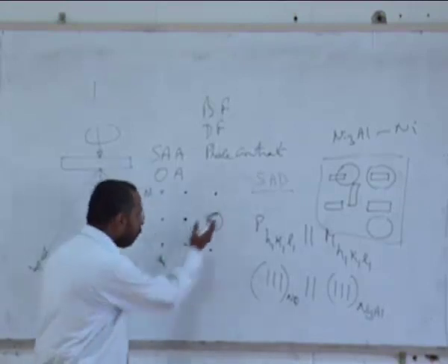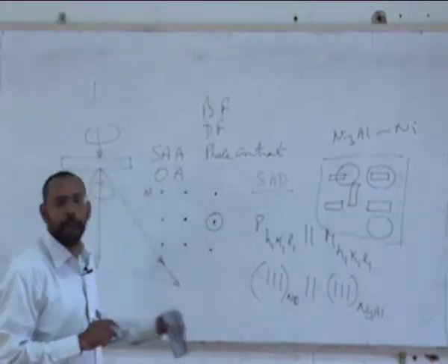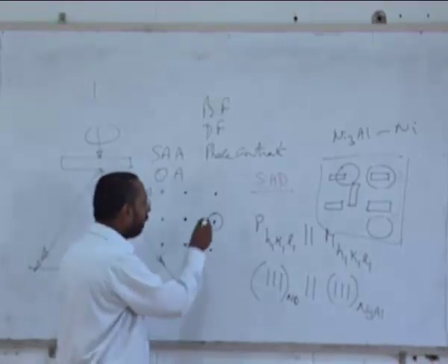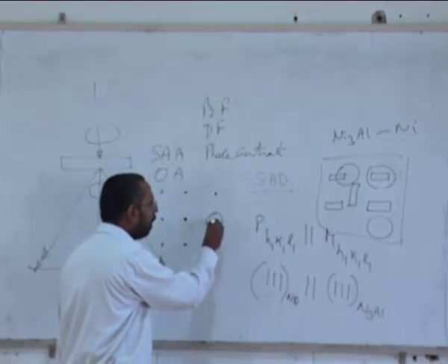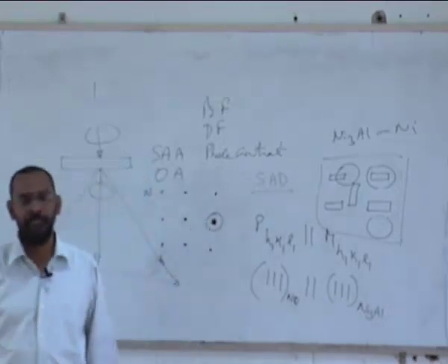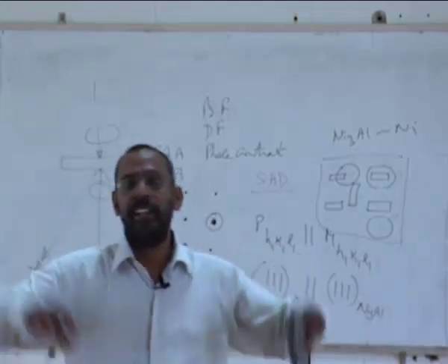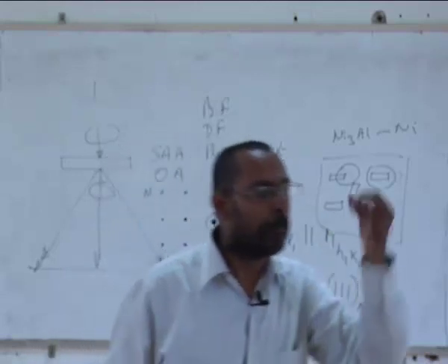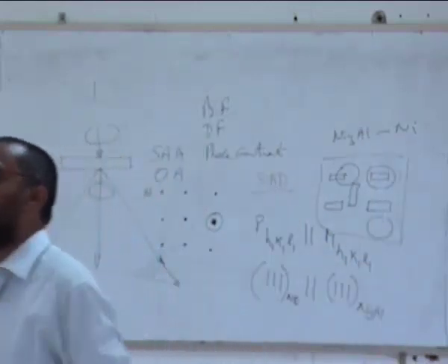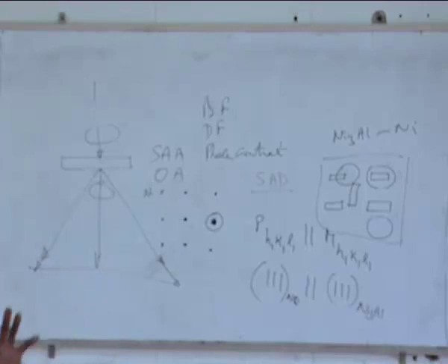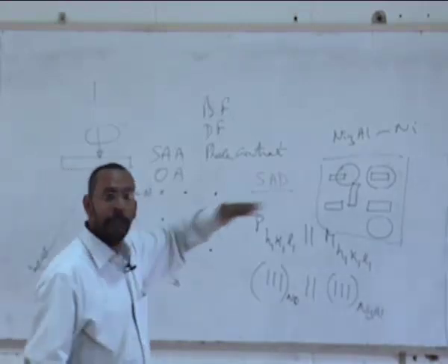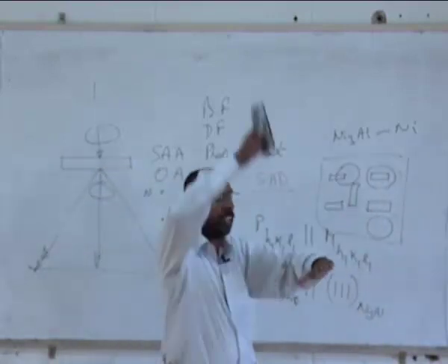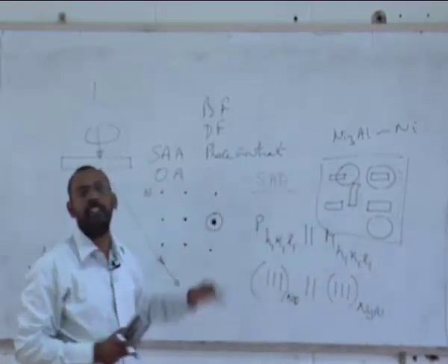There are advantages of moving this. I will not go into the details of that, but if you do that, what I get is all those precipitates which are giving diffraction, this way in which this particular plane is getting diffracted, they alone will look bright. Rest are all looks black. So you will have a black background, and in which the precipitates only will be shining like white particles. Not all precipitates, but only those precipitates whose plane which is exposed to the surface is such that it is giving diffraction pattern.